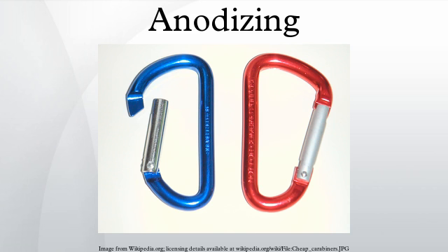Anodized zinc. Zinc is rarely anodized, but a process was developed by the International Lead Zinc Research Organization and covered by MIL-A-81801. A solution of ammonium phosphate, chromate and fluoride with voltages of up to 200 V can produce olive green coatings up to 80 µm thick. The coatings are hard and corrosion resistant.